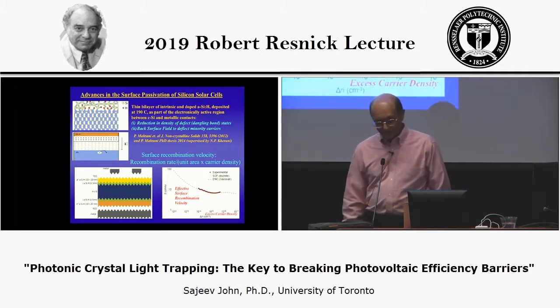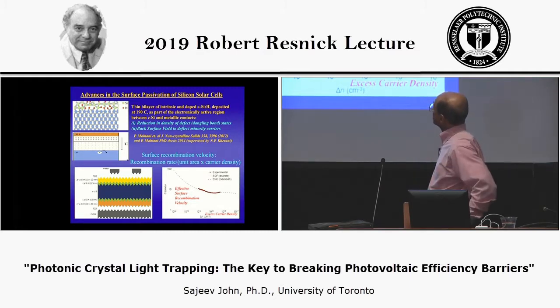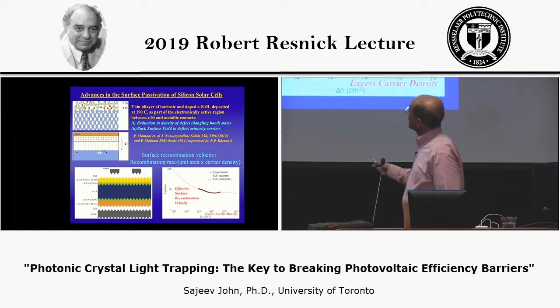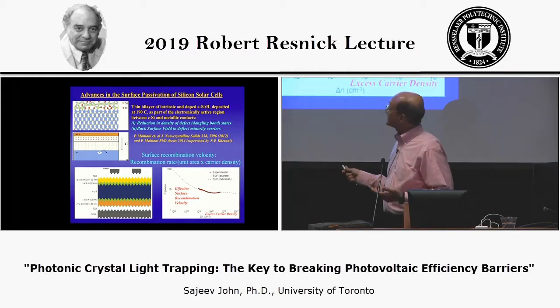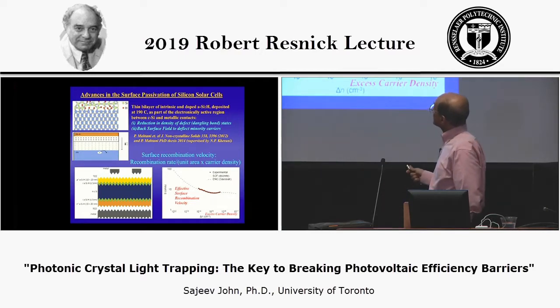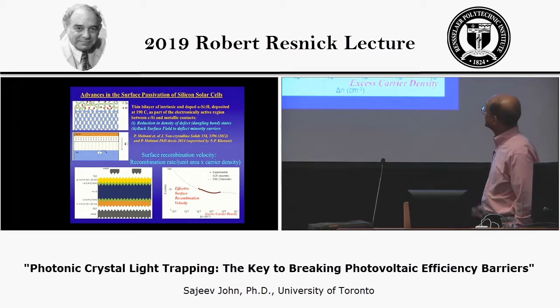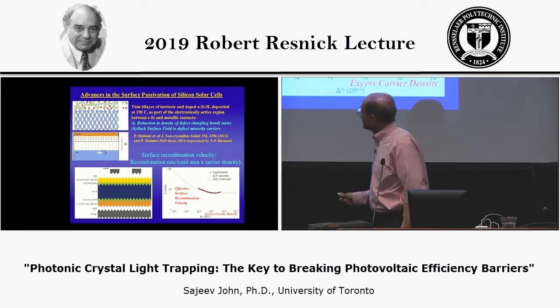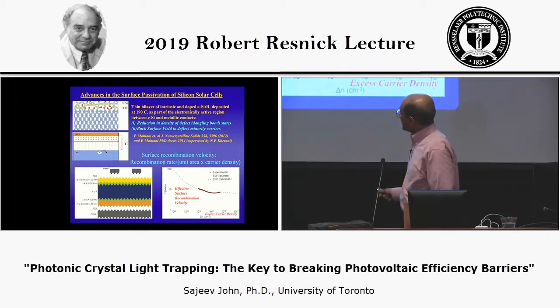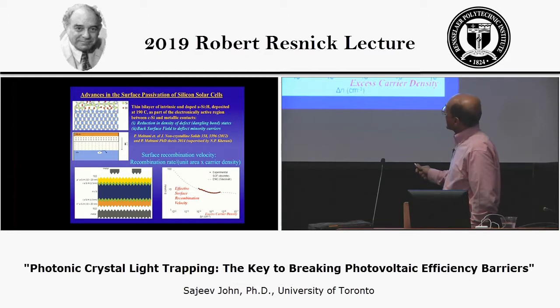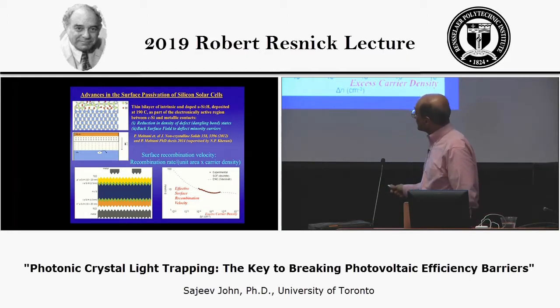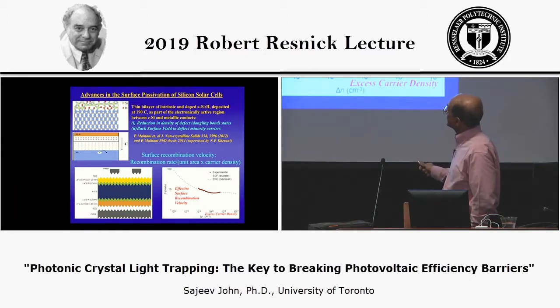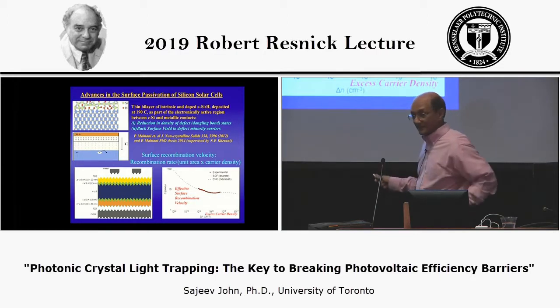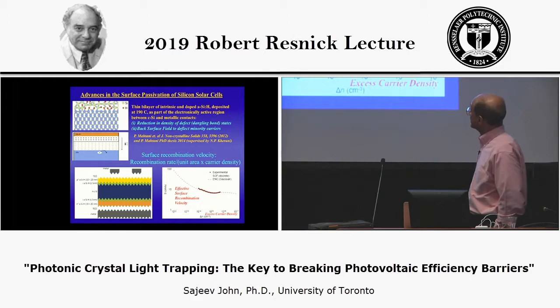The surface of silicon is a very important issue to deal with defects that can cause non-radiative recombination. Of course, if you have a surface, you're cutting bonds and there are dangling bonds there. You can try to remove some of those dangling bonds by various procedures. This is one that was used by my colleague in the ECE department at the University of Toronto, by depositing thin, nanometer scale layers of hydrogenated amorphous silicon as well as doped hydrogenated amorphous silicon to try and cap these dangling bond defects as much as possible. The doping region also creates a strong electric field near the surface that would deflect the minority carriers, which also have to get to the surface for non-radiative recombination to take place.